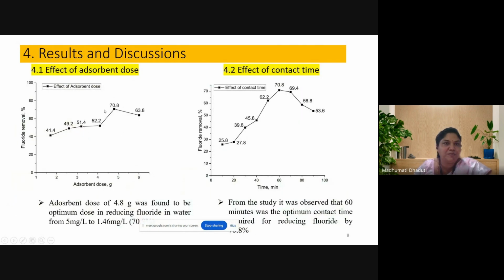So the adsorption studies, as I told, were done to optimize the dose and also to study the effect of contact time and pH. So in the optimization study, it was found that the adsorbent dose of 4.8 grams was the optimum dose in reducing fluoride in the water from 5 milligram per liter to 1.46 milligram per liter.